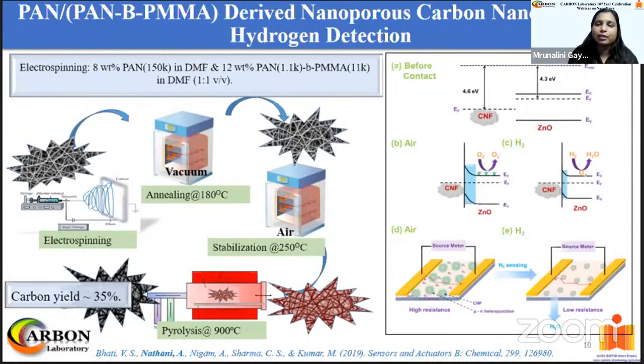Now, for the fabrication of the sensor, zinc oxide nanostructures were grown on P-type silicon substrate, onto which the interdigitated electrode pattern of gold was deposited using thermal evaporation. Then, carbon nanofibers homogeneously mixed in isopropyl alcohol were drop casted on zinc oxide nanostructure. It was found that the nanostructure-based sensor enhanced the sensing response to hydrogen gas at 100 ppm to 74%, which was only 3% in case of carbon nanofibers and 44% in case of zinc oxide nanostructure. This is due to the formation of PN heterojunction at the interface of carbon nanofiber and zinc oxide nanostructure. Further, presence of oxygen functional group on carbon nanofiber surface contributed in enhancement of sensing performance.